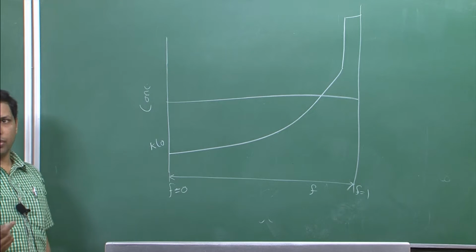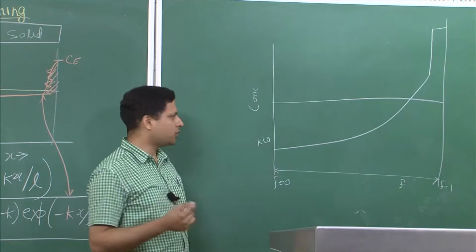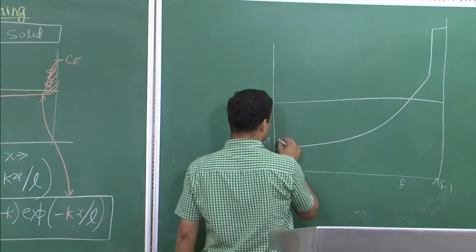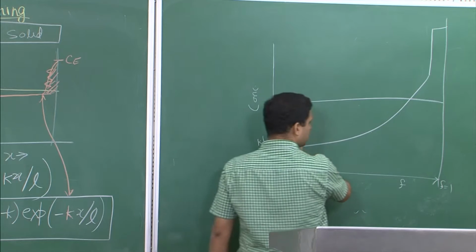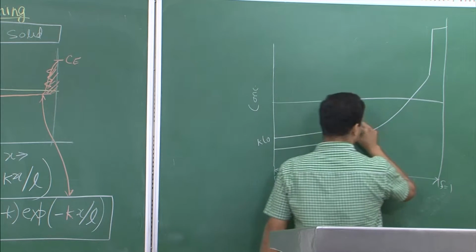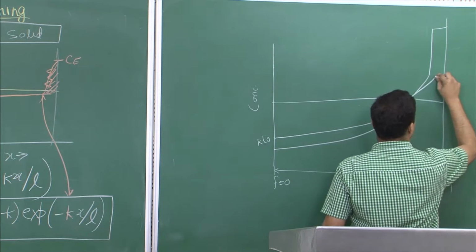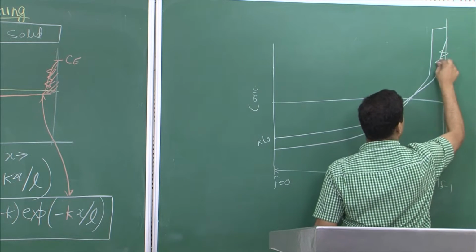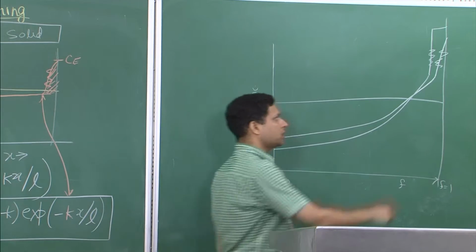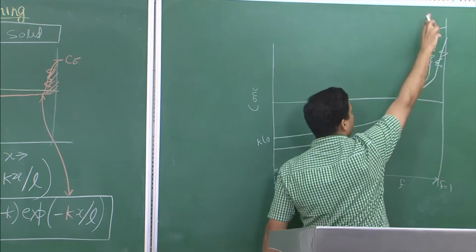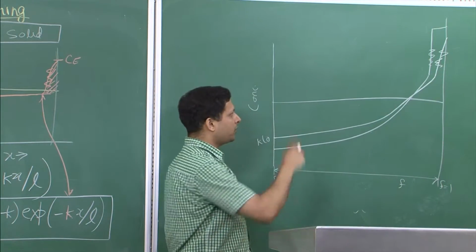And if you keep increasing the amount of convection, what happens to this plot? That is where the K effective becomes very useful, which I did not explicitly mention earlier, but let me show it now. I am drawing this zigzag to show that the concentration increases sharply over there and probably it is out of scale.